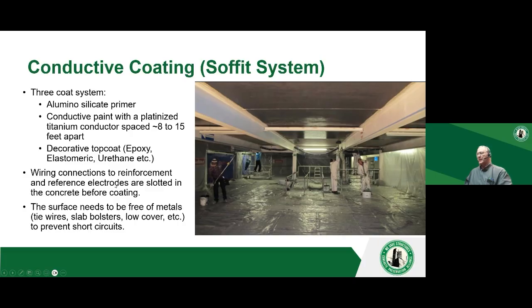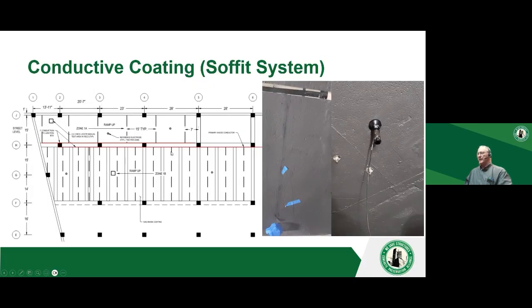Your wiring connections to the reinforcement, all that stuff is done before you put your primer on. Here's a layout. What you can see here is you use those little push pins again, those Christmas tree anchors. This is the anode wire that is like a conductive wire. So here we have beams, so they use a conductive wire in between, and it throws current to the conductive coating, which will protect on either side. Typically 15 feet is about as wide as you want to put these wires, and you connect them up to a conduit on the ends.